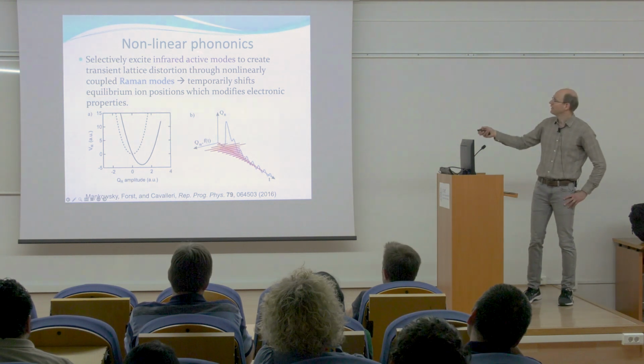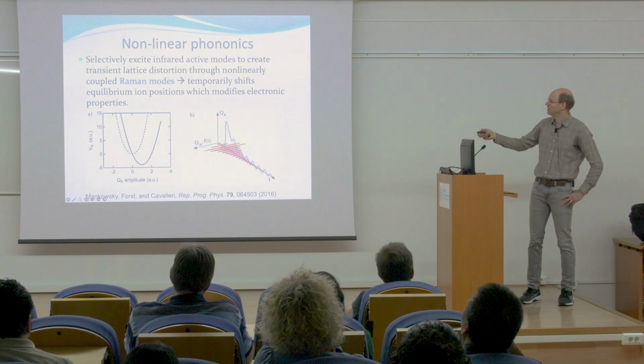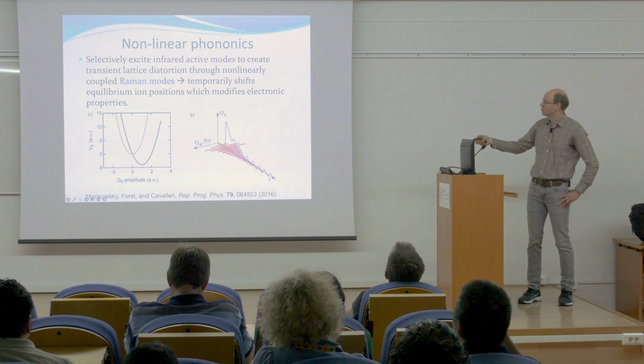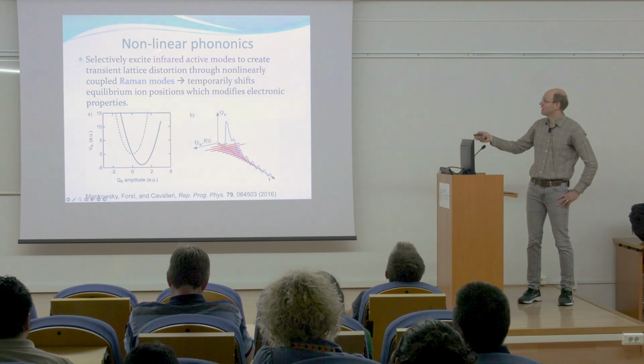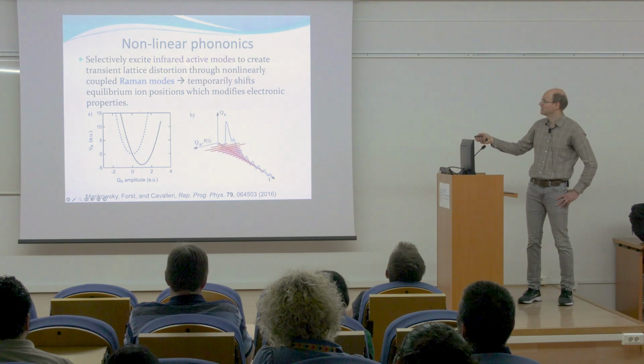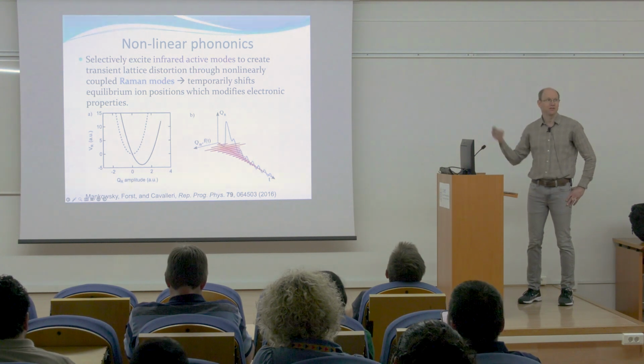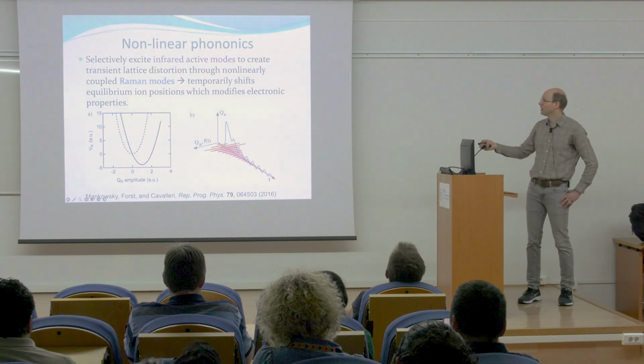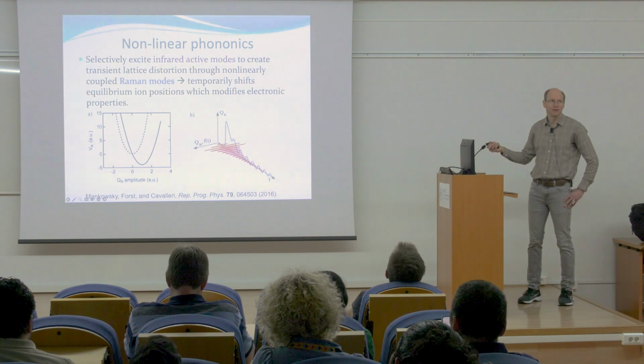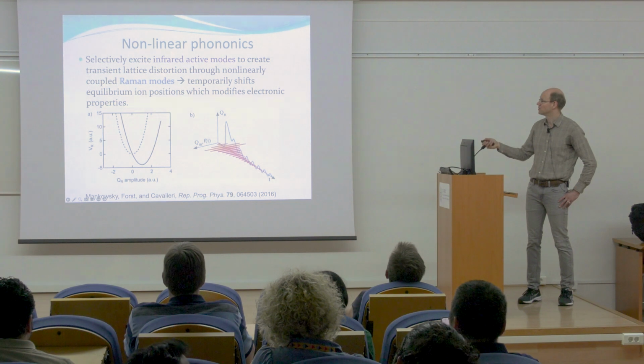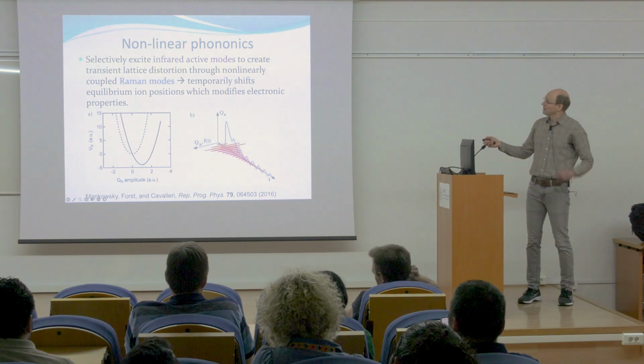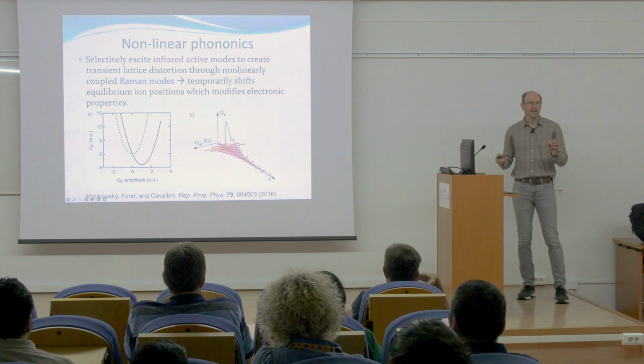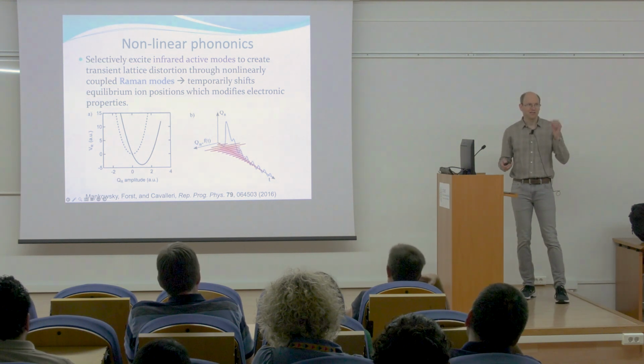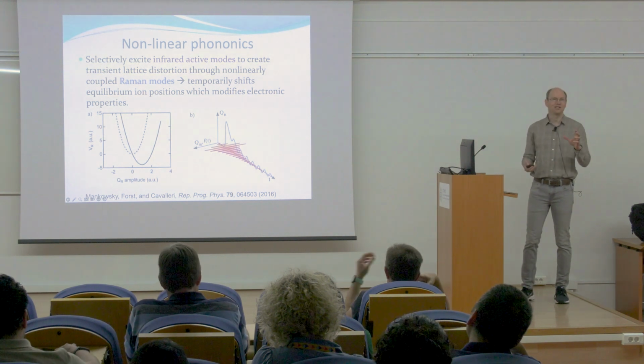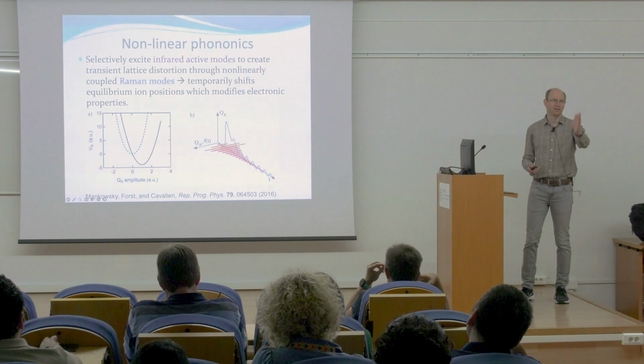So in nonlinear phononics, what one deals with in a system with inversion symmetry are 2 main types of lattice excitations. So there are so-called infrared active modes. So these couple directly to light. And then there are Raman modes, which couple only at the second order. So they're not directly excited by the light. They have different parities associated with them. So nonlinear phononics, you shine light of low frequency but large intensity. So the low frequency resonantly excites the phonons, and the large intensity creates a large amplitude distortion of the phonons.